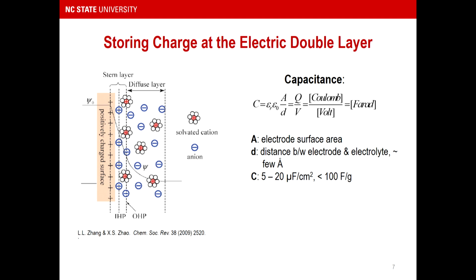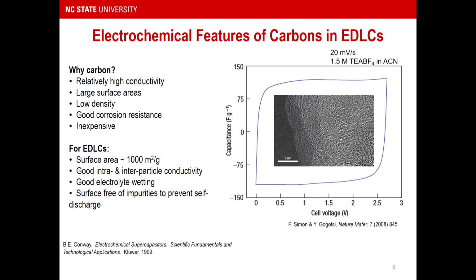The double-layer capacitances range in magnitude from about 5 to 20 microfarads per square centimeter, giving rise to specific capacitances of about 100 farads per gram or so. And so this is the mechanism by which this works. And the materials of choice have always been carbons, different types of carbons, which offer very high conductivity and large surface areas, good corrosion resistance, and so forth. And these materials behave electrochemically almost exactly as an ideal capacitor would behave. And this is a cyclic voltammogram of activated carbon at 20 millivolts per second. And you can see that it offers a constant capacitance over nearly the entire potential range.